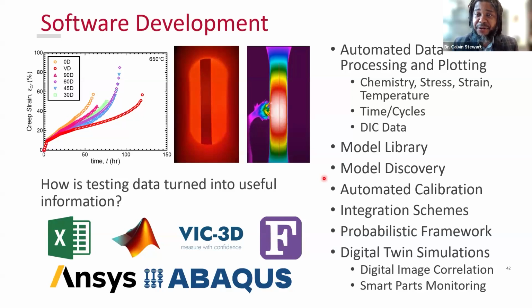With the data that we generate, whether it's conventional ASTM tests or 3D digital image correlation, where we have matrices of data at every capture point and multiple images for every capture point, we have to develop software tools to regress, to clean our data up, so it becomes something that we can use, right? So multiple languages, whether it's Python, Fortran, or even integrating finite element code such as ANSYS and Abaqus, so we can do digital twin simulation, so we can match the experiments to the simulations and see if the models are real, if the models that were designed 50 years ago actually capture the real world. So many of them don't, right?